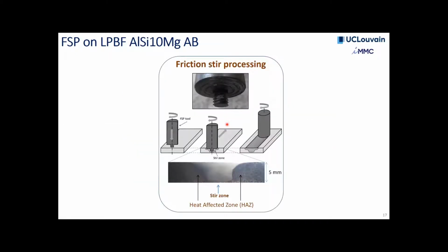Let me walk you through a bit what friction stir processing is. So friction stir processing, you have a tool here that's made of a shoulder here and a pin here. And this pin penetrates into the material until the shoulder is on top surface, and then it kind of stirs the material and advances in that way. So that can be used for welding, but it can also process the material, make a friction stir zone, which is called the stir zone.